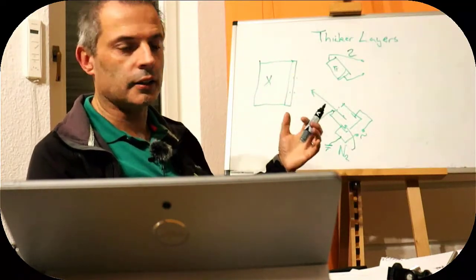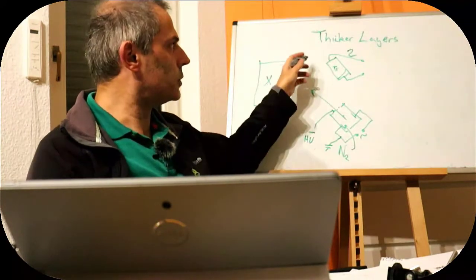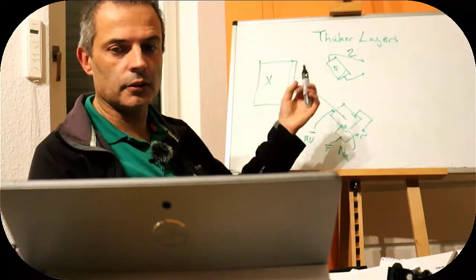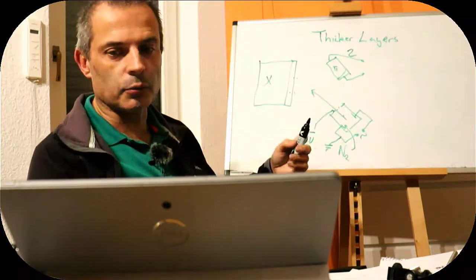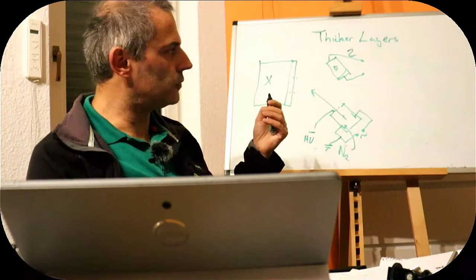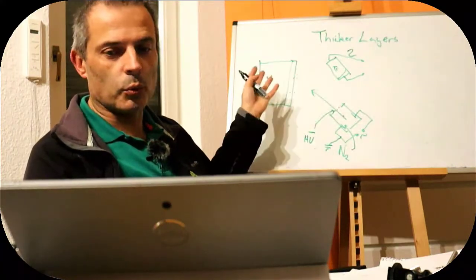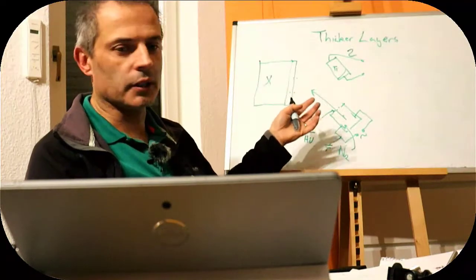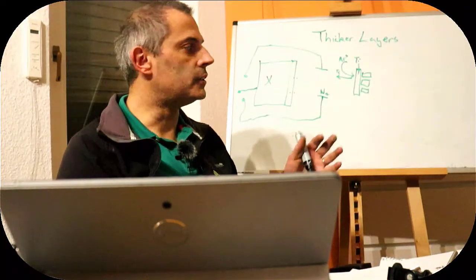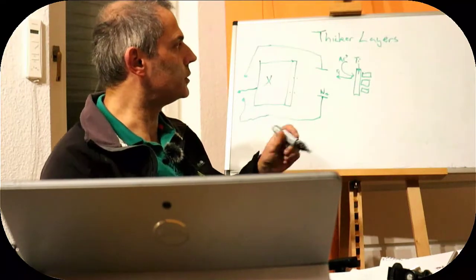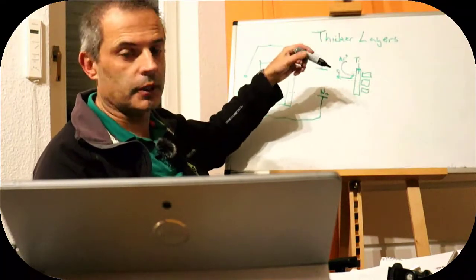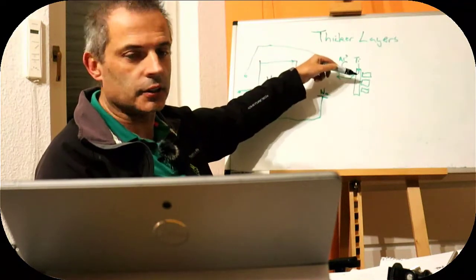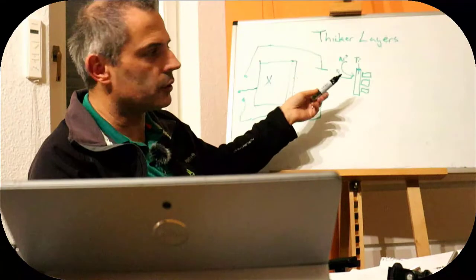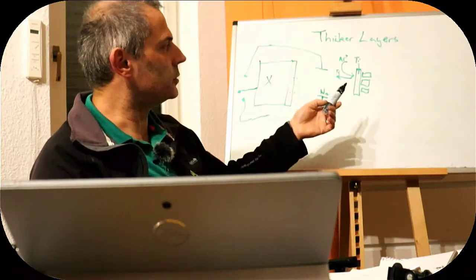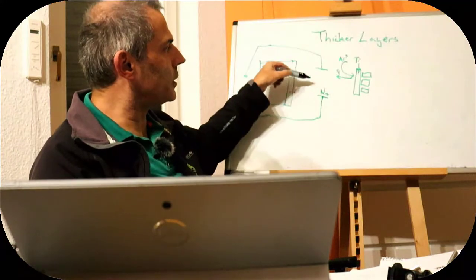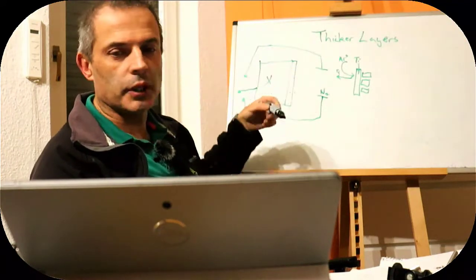If we want to add oxygen to the film, we can add a little bit of oxygen to the chamber, or we can add a third source. The problem with having everything in one source is exactly as before. We are forced by physics to take what we get, and then we might not get what we put in. This is a slightly simpler setup, where we could take the titanium metal and sputter it instead. So we're shooting argon ions into the titanium, making argon atoms, maybe some titanium atoms, maybe some titanium ions too. And we allow them to travel through a nitrogen plasma, which we have in between.